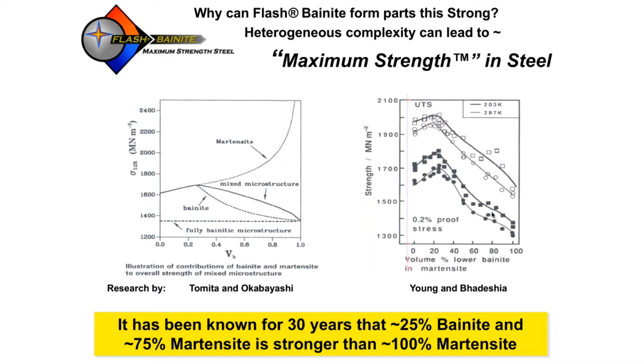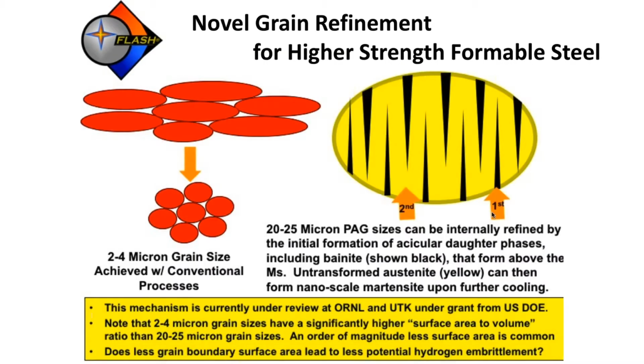So working with Professor Babu and the students down at University of Tennessee, we believe we've got an explanation as to how this technology actually makes steel 7 to 10% stronger. Everybody understands that grain refinement will lead to higher strength in steel. And if you look at the pictures on the left, the red ellipses are meant to represent some heavily cold worked steel where the grains have been elongated. And as those grains elongate, they're fed through a continuous annealing furnace with the goal of refining the grains to 2 to 4 micron sizes, which comes with it all the well-known and well-understood logic that goes along with grain refinement and steel heat treating. This is what continuous annealing lines are all about.